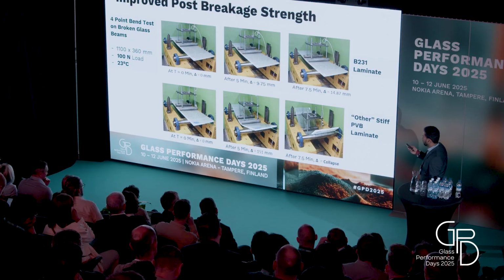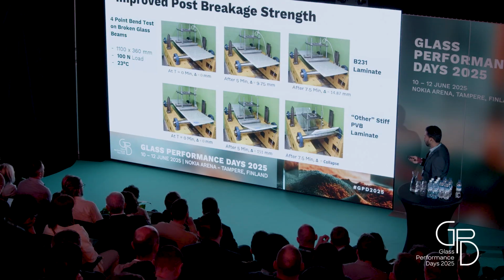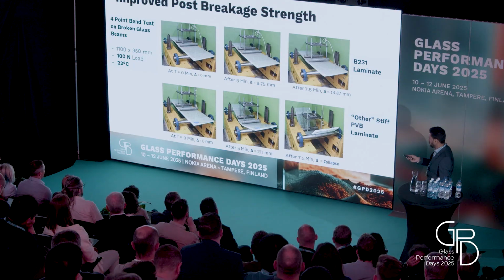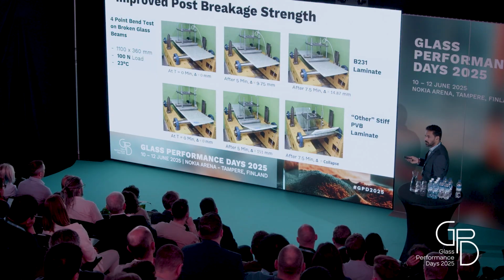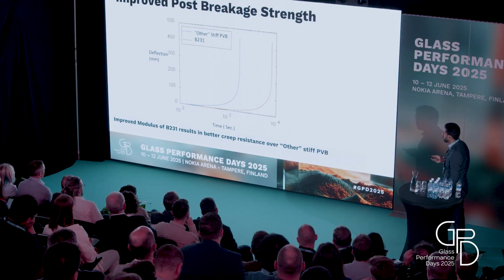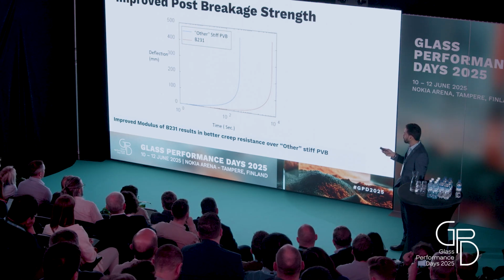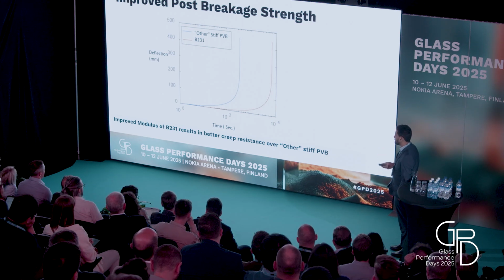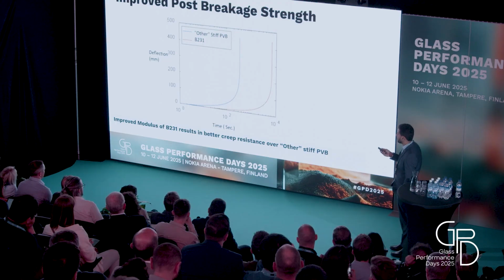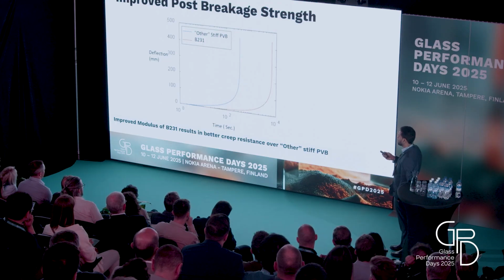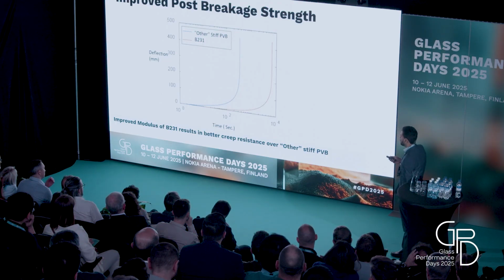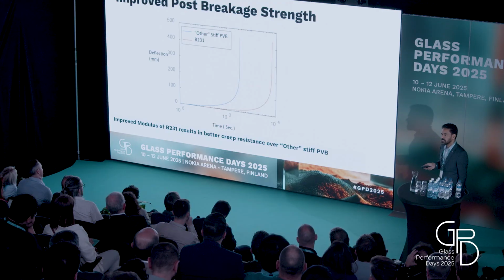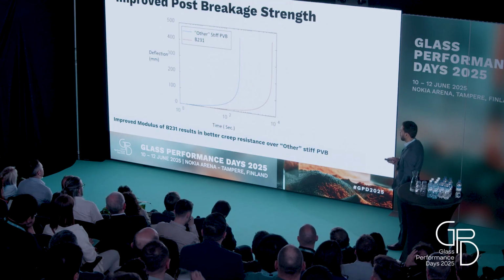On the top, we have the B231 laminate, which is the improved stiff PVB. And at the bottom, we have the other stiff PVB. And you can see there is a big difference in the creep behavior. The other way is to plot the curve between the deflections and the time. Here you can see there's a drastic difference in the creep behavior of the existing PVB and the improved stiff PVB.